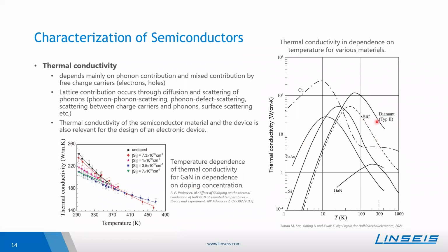On the right, you can see the thermal conductivity, also in dependence on temperature, for various materials. Copper is also shown here, and silicon carbide, gallium arsenide, and silicon, where you can especially see that all of the curves have in general a similar shape, so that first the thermal conductivity is increasing. At some point, the maximum is achieved, and then for increasing temperature, the thermal conductivity decreases. So one can clearly see that the thermal conductivity depends on temperature and also on the kind of doping, and also on the doping concentration.